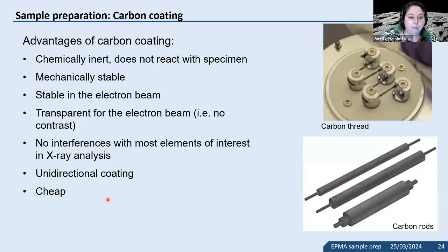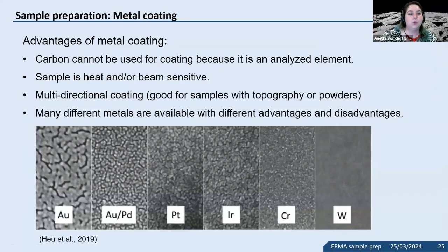It's also cheap. The downside can sometimes be if you have porous samples or three-dimensional ones, that it's a unidirectional coating, meaning that the sides are not necessarily well covered. So that can be an advantage of metal coating, where you use sputtering for it. So if I have to analyze powder or something, I usually find that sputtering is better. We usually don't like sputtered carbon though. So just as a comment for that.